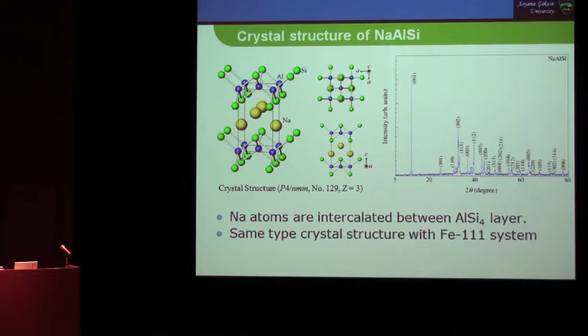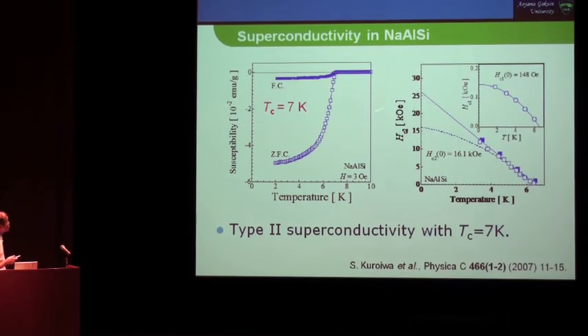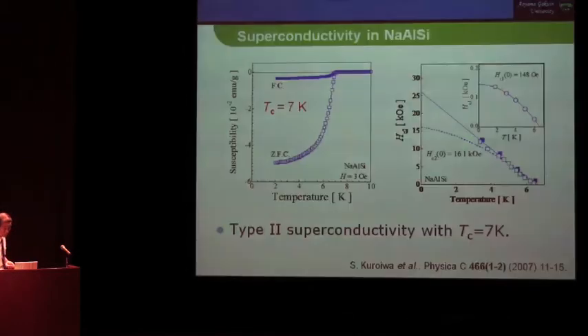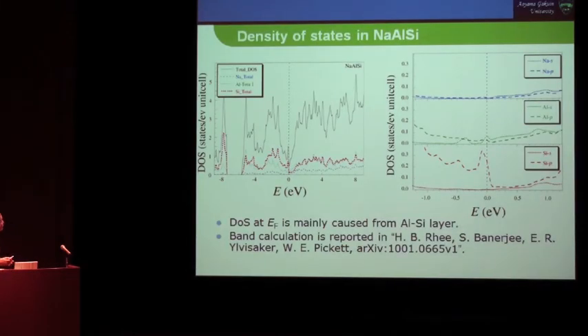And TC is about 7, and it has type 2 superconductivity with TC 7 Kelvin. Recently the Pickett group has published data of the band structure, and the density of states in sodium aluminum silicon is here, and TC is reasonable. DOS at EF is mainly caused from the aluminum silicon layer.